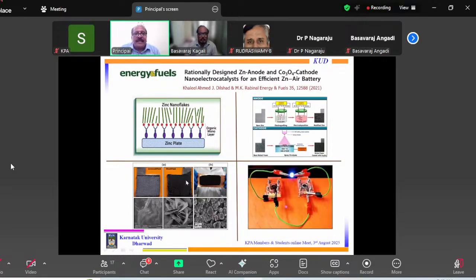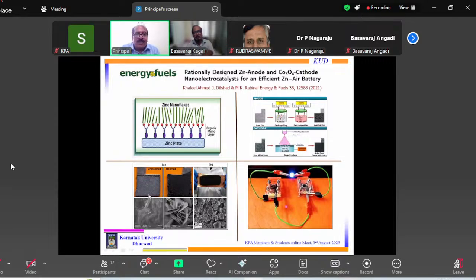So what you need in a zinc air battery is a very large surface area in order to have a good battery. We have a zinc plate. We wanted to deposit zinc on that to make a zinc air battery, but we created organic monolayers and then tried to deposit. What we found is we can deposit very large area zinc nanoparticles by doing so. You can see chemically unmodified zinc deposition. Once you modify with the molecules and deposit, it becomes more dark.